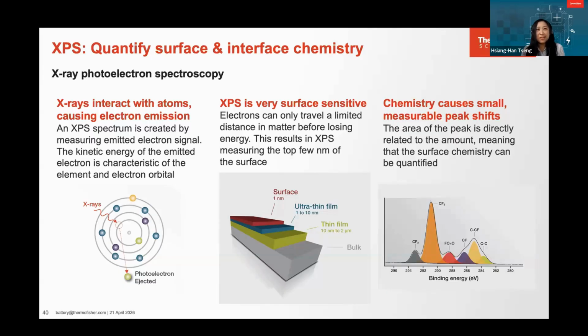Now, the instrument itself measures the number of the electrons emitted at the particular kinetic energy to produce a spectrum where the peak areas are proportional to the amount of element present in the sample. So that's very nice, but what makes this technique particularly useful for us is that the changes to the chemistry will directly affect the binding energies of the electrons in the atom, which we then detect as changes to the kinetic energies of the electrons emitted from the surface.